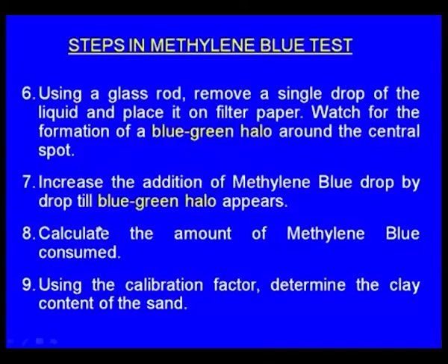Now, how much methylene blue is consumed? That we have to find out from the burette. From that, calculate the amount of the methylene blue consumed, and based on the consumption of the methylene blue, using the calibration factor, determine the clay content of the sand. Remember that methylene blue does not react with the dead clay, it reacts only with the active clay. So, that is how we can find out the active clay in the green sand.